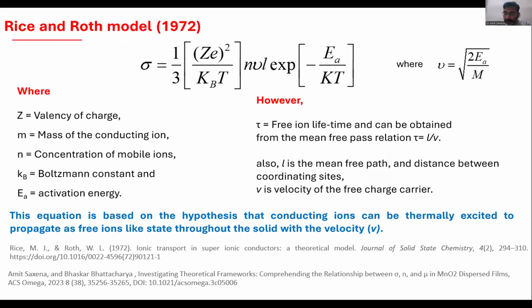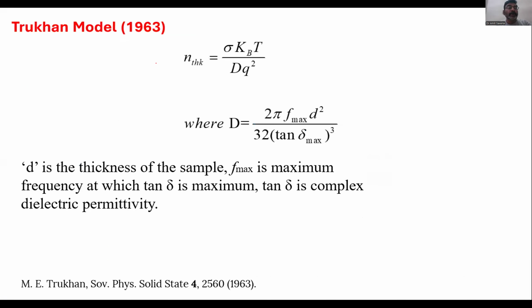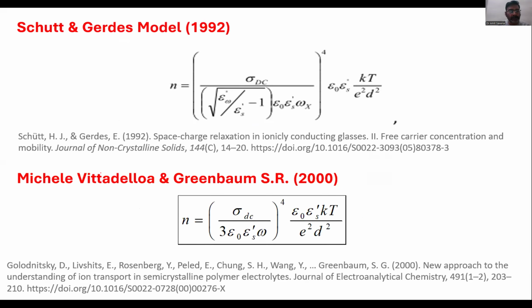One is the Rice and Roth model, which is best suited for material which is crystalline in nature, more crystalline, or maybe partially amorphous. Another is the Trukhan model, which is based on your diffusion constant value, D, which can be calculated from the tan delta graph. And another is the SG model. I'm not giving more insight on the other two models, although I have included them in my slide. But the SG model is one of the most popular, or the recent one, which people are using to find the value of N. So all these three models, all these values can be analyzed directly from the impedance data.